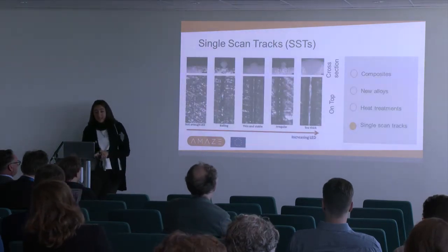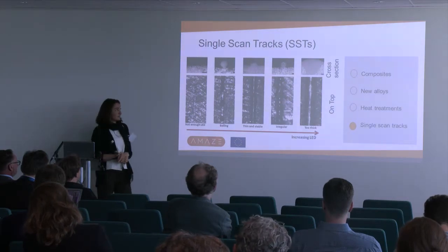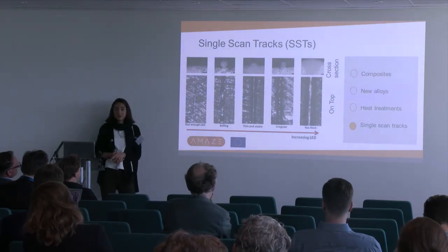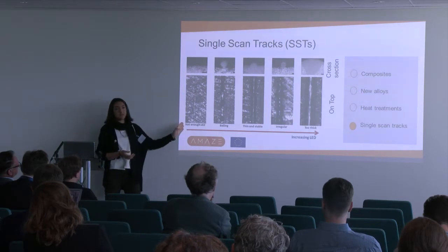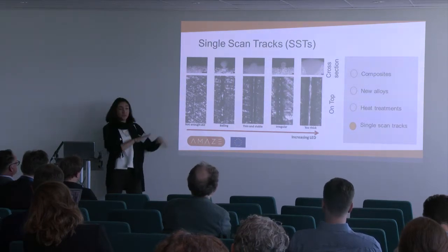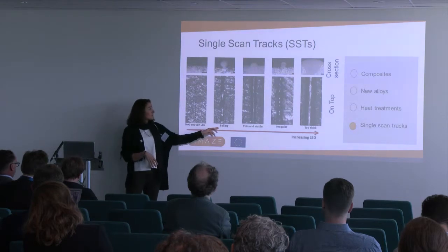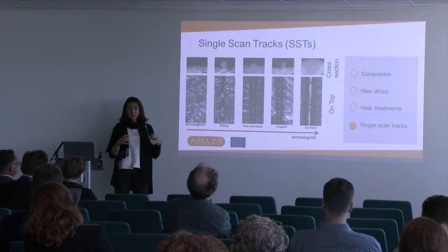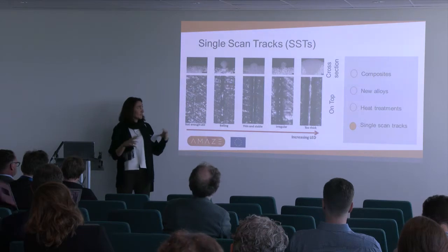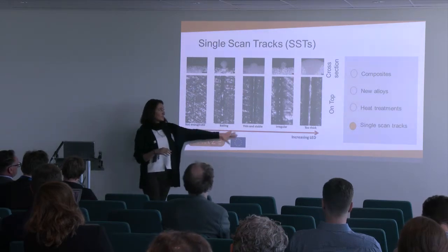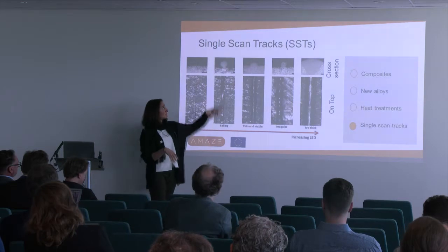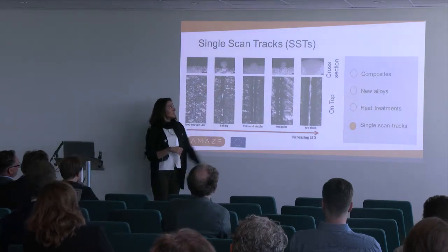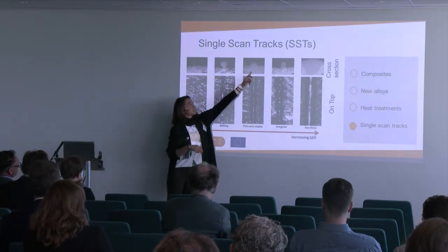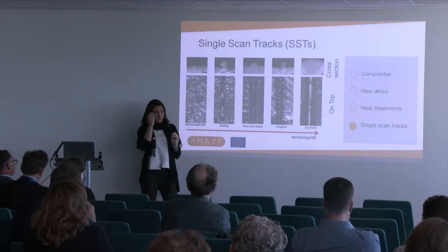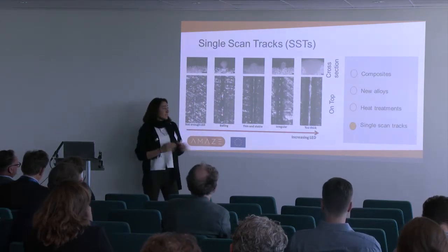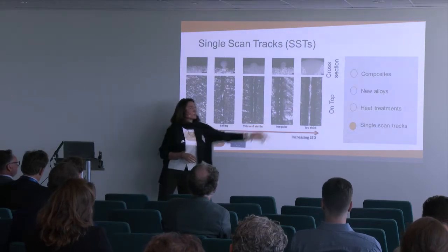When we analyzed these scans, we found mainly five morphologies. The first is not enough melt: in this case, the power was not enough to melt the scan. Then we could see balling, where the scan breaks into separate drops because of surface tension effects. Then we have a thin and stable scan, which seems promising. Here we have also the cross sections, where the depth of the scan is quite similar to the height of the scan. Then if we increase the energy density, we go to irregular scan.